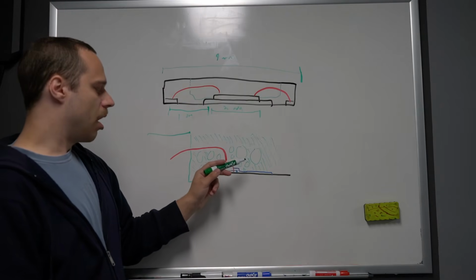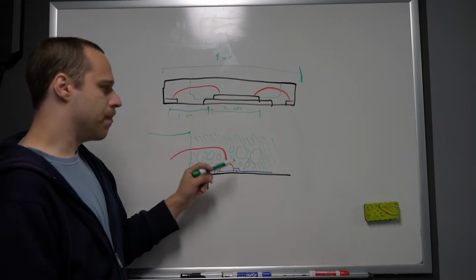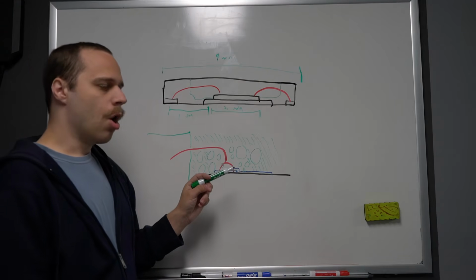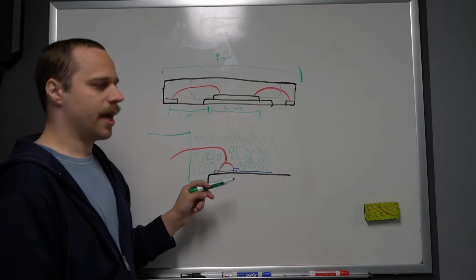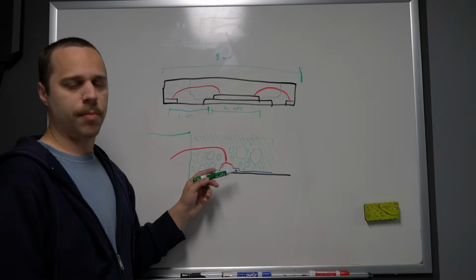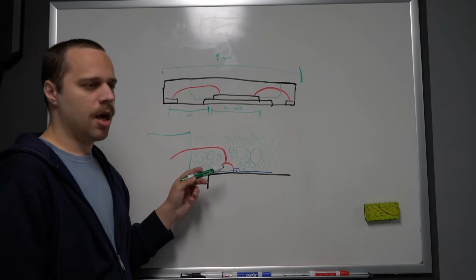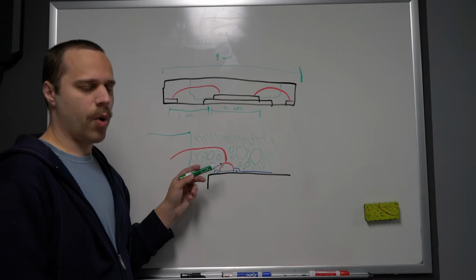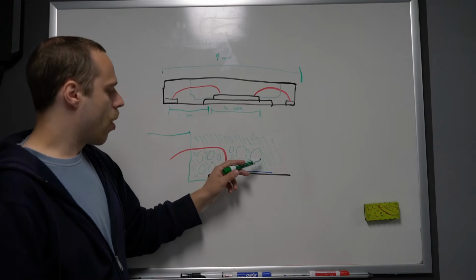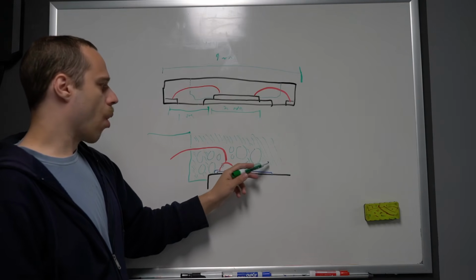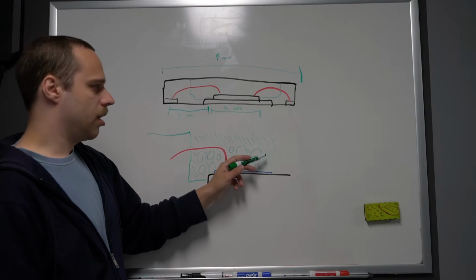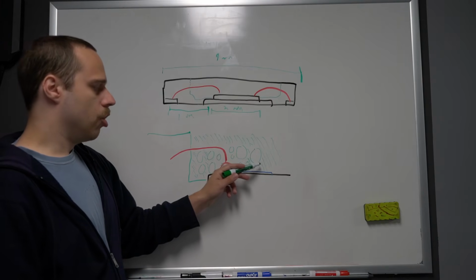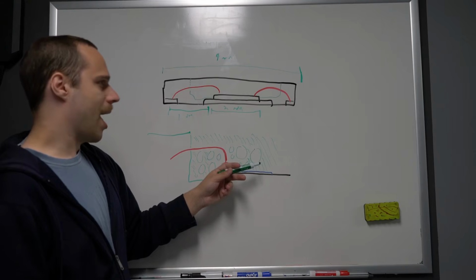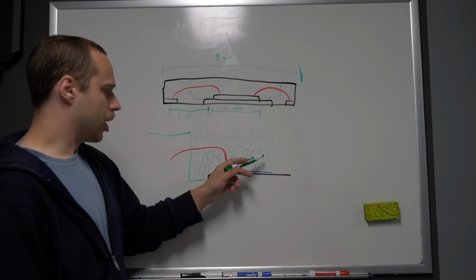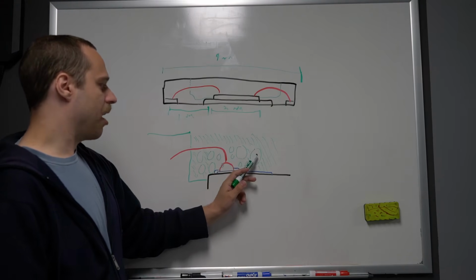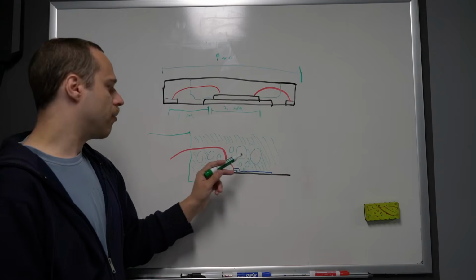This is typically done if you're just trying to recover a bare die for deprocessing, or if you're trying to depackage a gold bonded device. This is typically done with concentrated nitric acid, which is a strong oxidizer as well as an acid, and this will allow us to take all of the organic filler material and oxidize that into CO2 and water and other easily removable etch products, and then the silicate filler can just be washed away with a solvent.